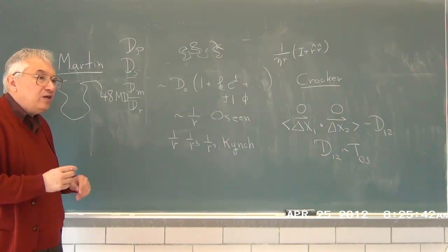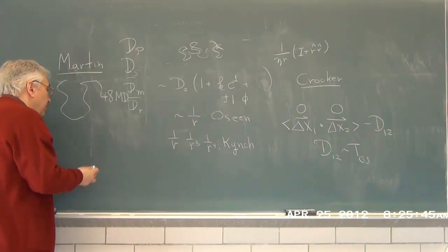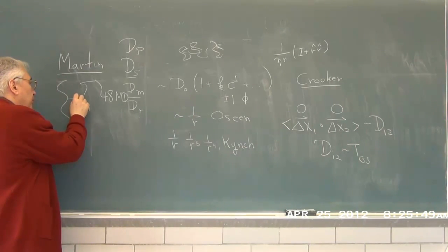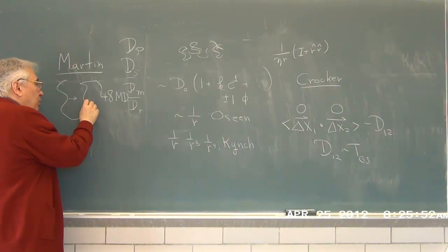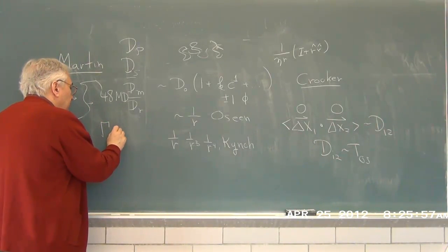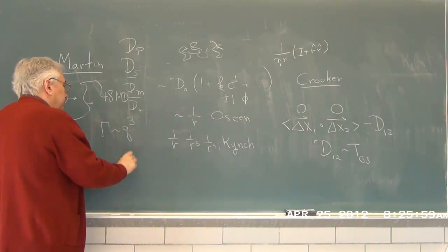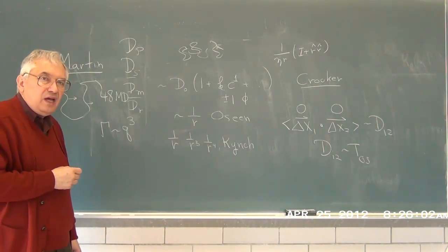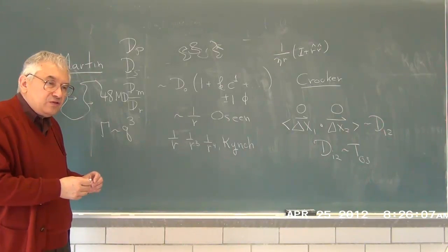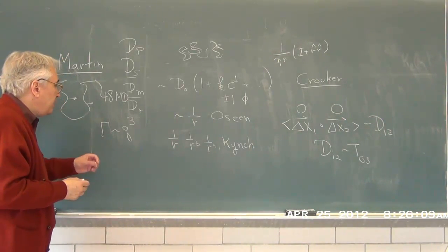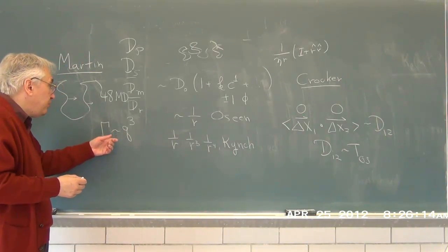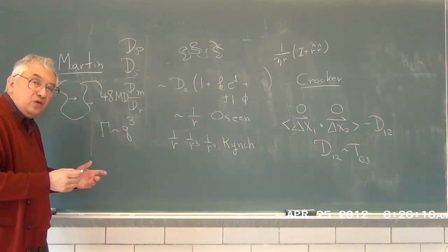This is something we talked about back in about chapter 8, and what we find is that for reasonably large Q, you can see the motion of one part of the polymer with respect to the next, and the relaxation rate goes as Q cubed. That is, the larger the Q is, the smaller the scaling distance is. If you had a diffusive process, a rigid object moving, you'd see Q squared. Here you see Q cubed.